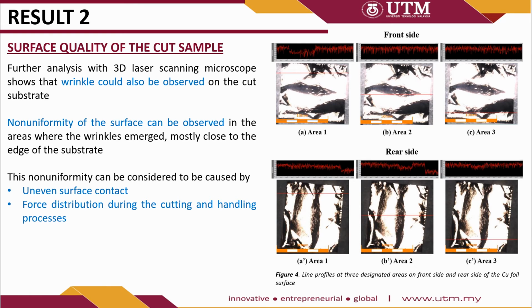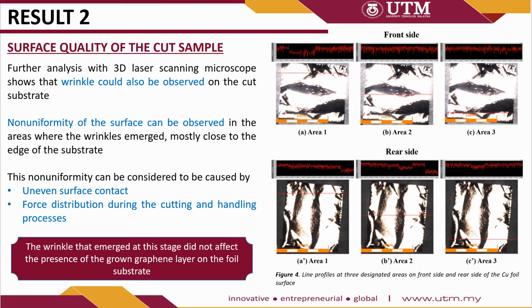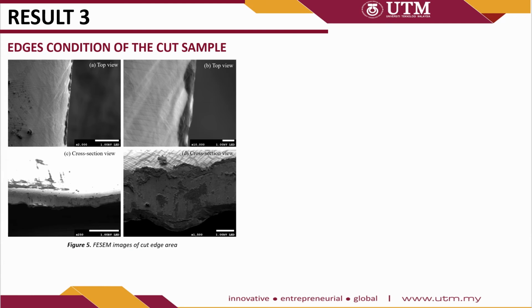This non-uniformity can be considered to be caused by uneven surface contact and force distribution during the cutting and handling processes by using scissors and tweezer respectively. However, the wrinkle that emerged at this stage did not affect the presence of the grown graphene layer on the foil substrate. Next result is the edge condition of the cut sample.